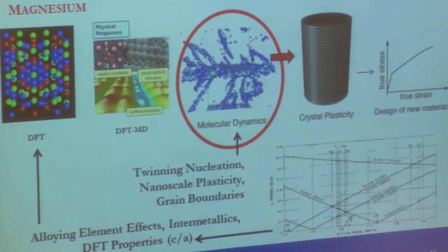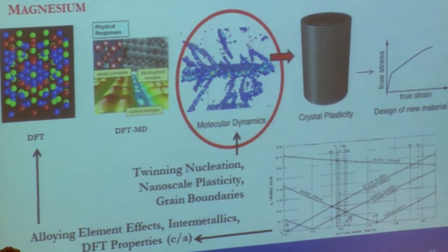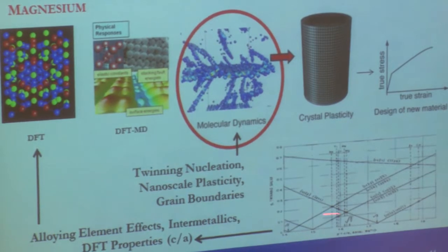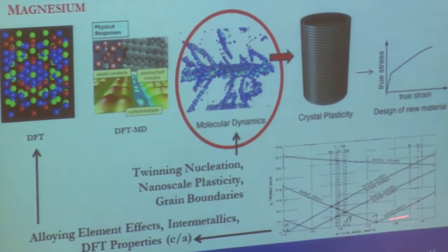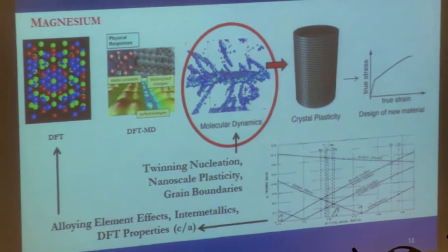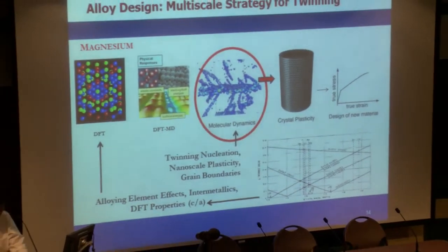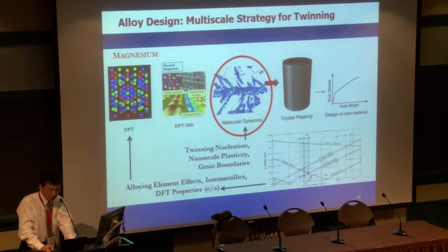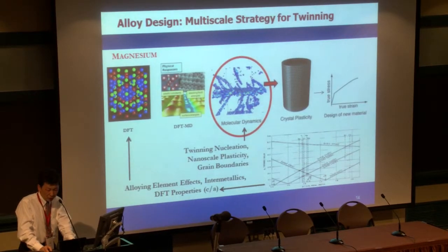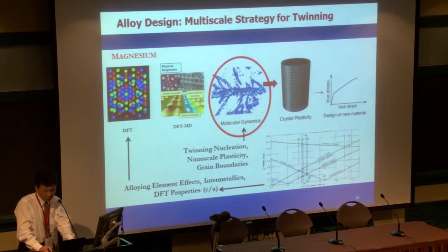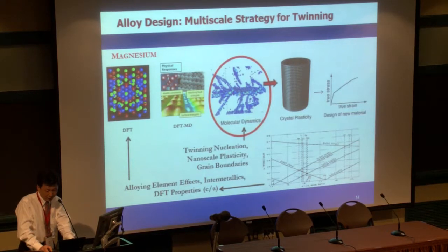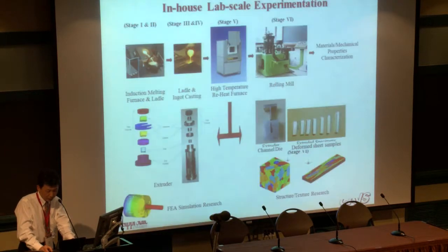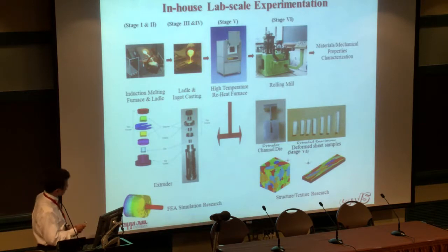And also the other one is in the design, because twinning system, there's a 4 dominant twinning system. And we look at in different design, look in the C/A ratios and see how we can design with a better ductility of the magnesium, which has no rare earth type elements. Rare earths, people been very popular doing that with like cerium and other material.